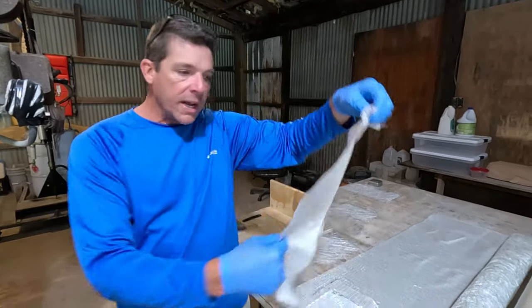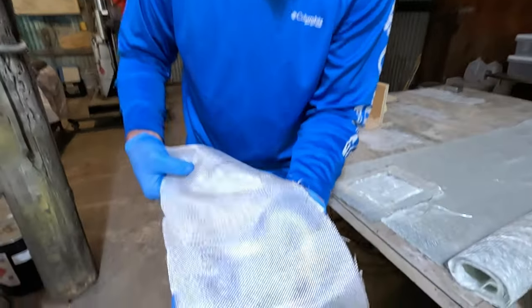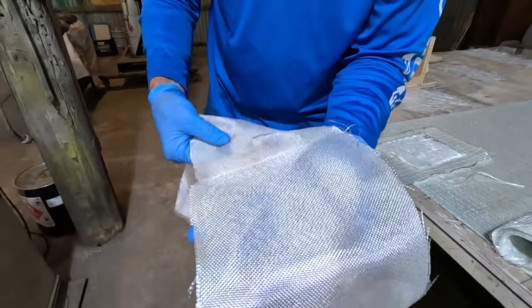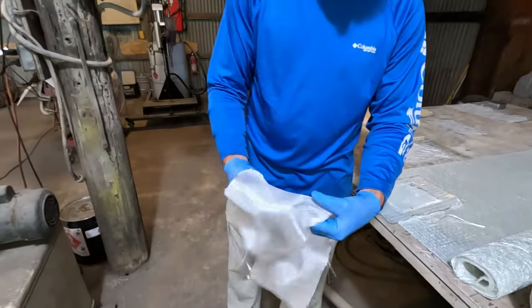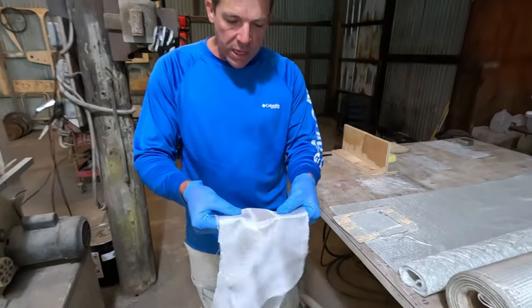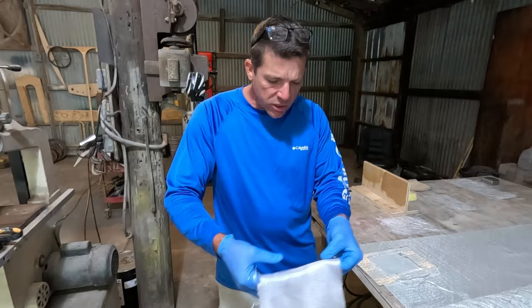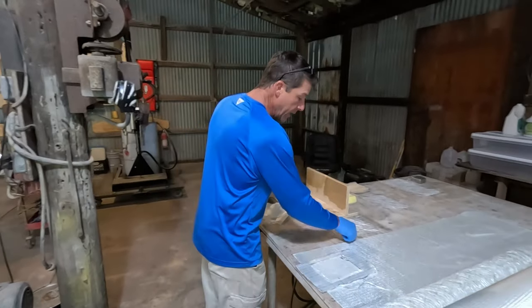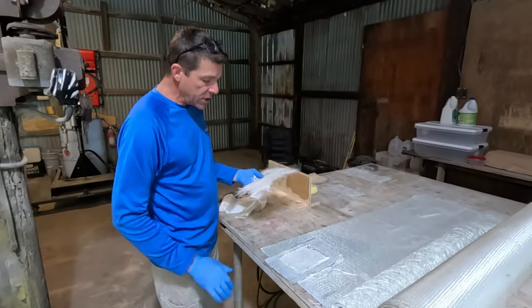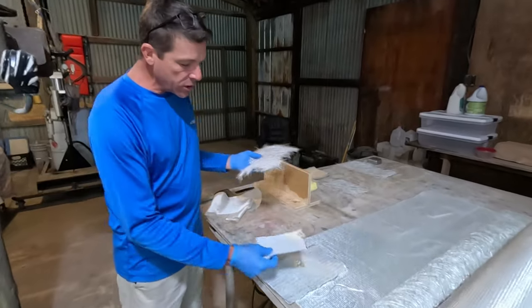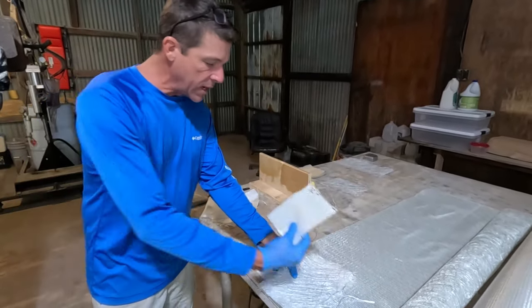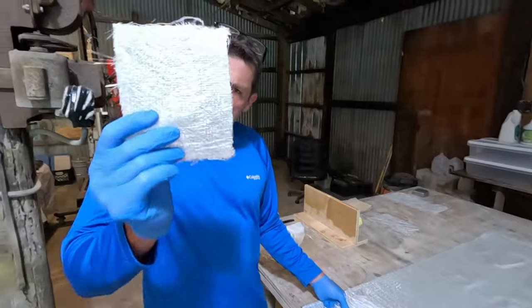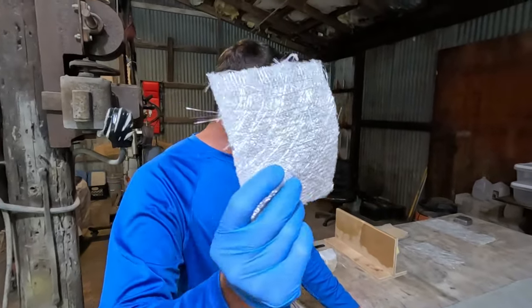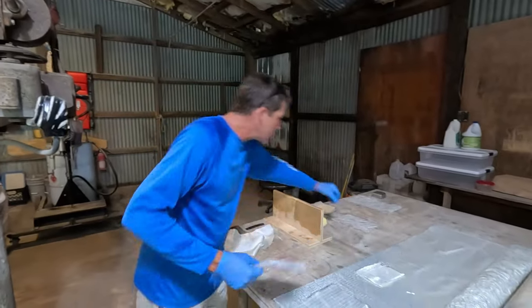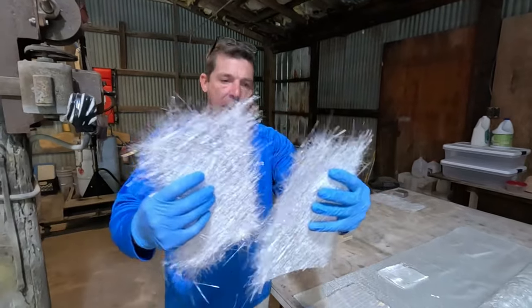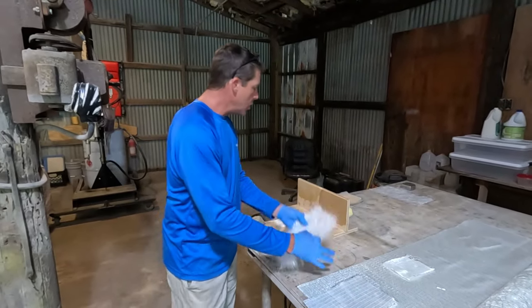What I do recommend with epoxy is a finishing cloth. This is like a 6-ounce finishing cloth. It's woven together. It will bend and conform, and it gives you a very nice cosmetic finish. The way things work, you can stack the 1708 on itself. You can also do one layer. You could do a layer of 1808 and 1708, although there's no reason for that because that has the mat underneath. You can also stack layers of mat one on another, no problem.